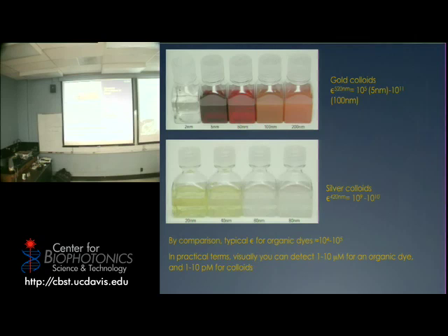Are you guys familiar with the concept of extinction molar coefficient? It is essentially a chromophore-dependent value that gives you an indication of how much light you can absorb. The larger it is, the more intense the color at a certain wavelength, which basically means it's easier to distinguish at low concentration. Even the best chromophores you can find have an extinction molar coefficient of the order of 10 to the 4th, 10 to the 5. So say 100,000 maximum, maybe 150,000 maximum.